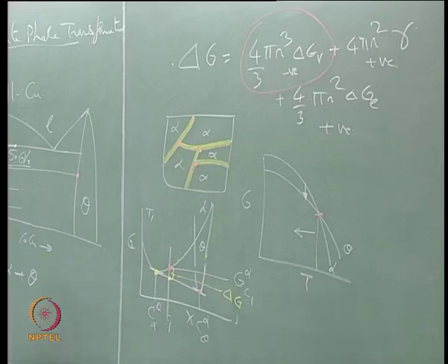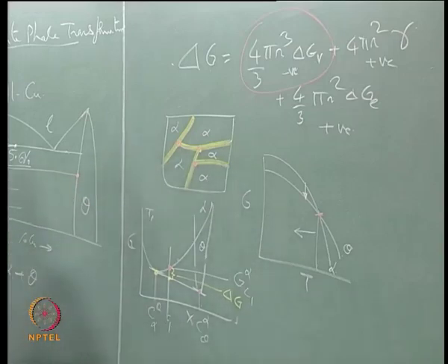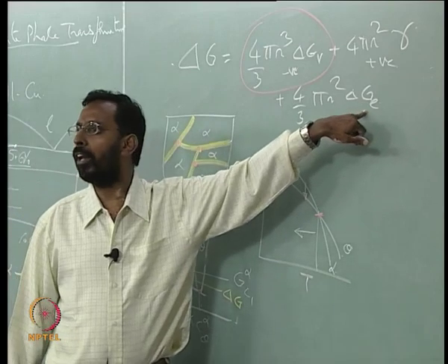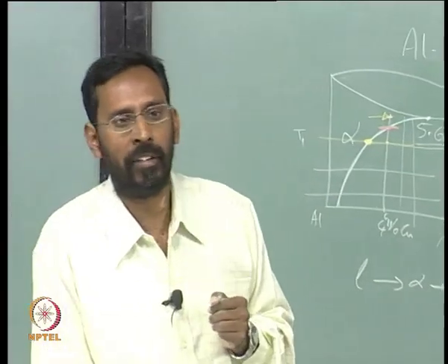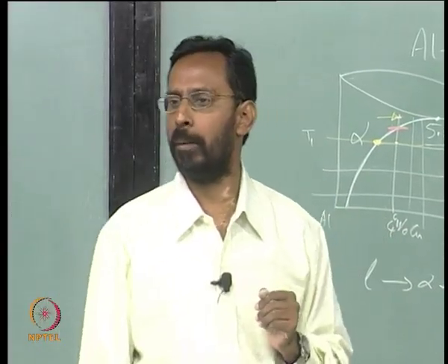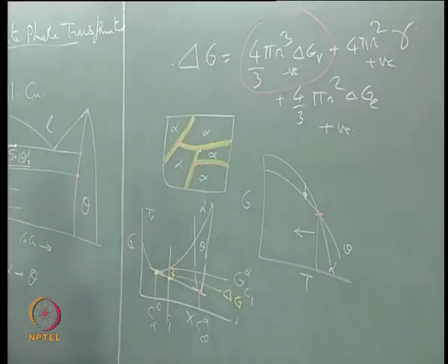Second, these regions have a more random structure. Because of the randomness and the open structure available at the grain boundaries and triple junctions, the strain can be accommodated much more easily, and as a result you will see most of the nucleation occurs at the grain boundaries or the triple junctions.